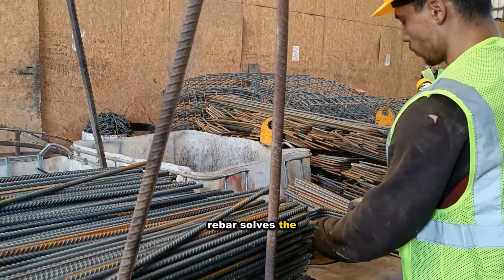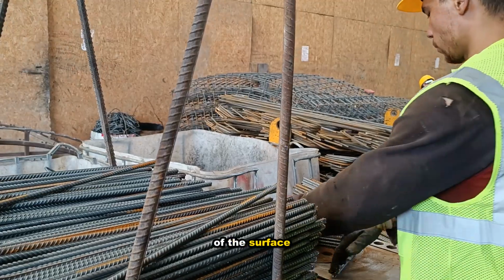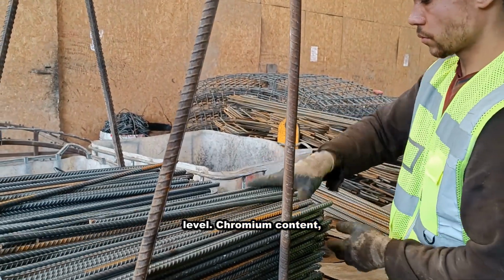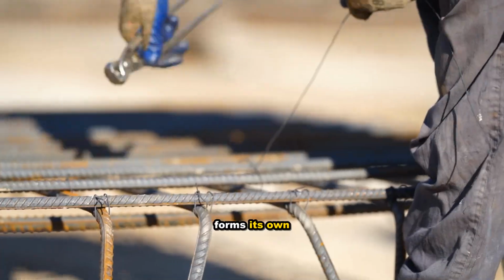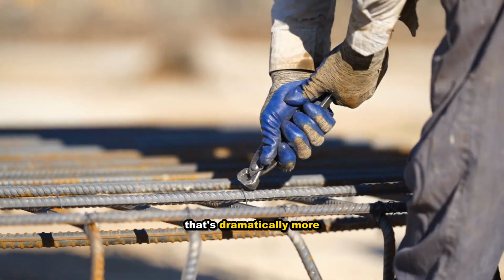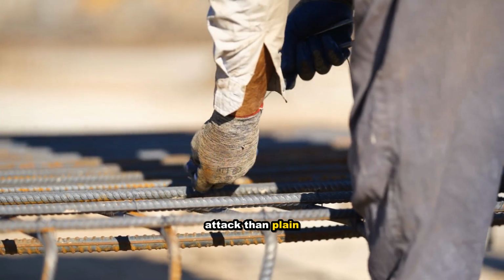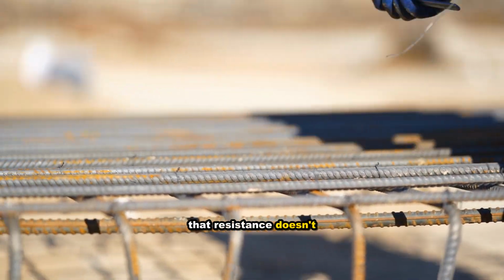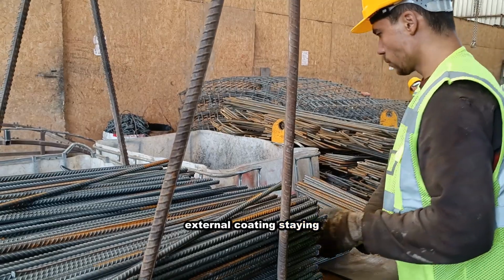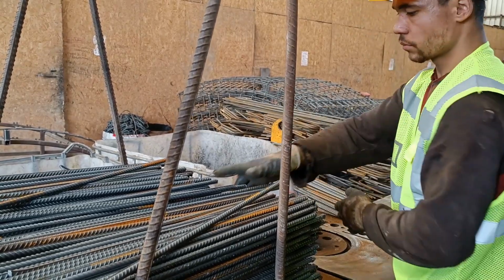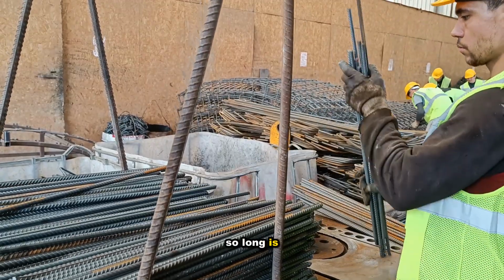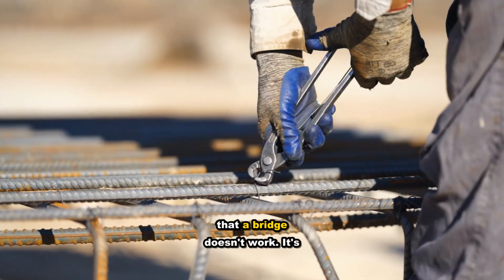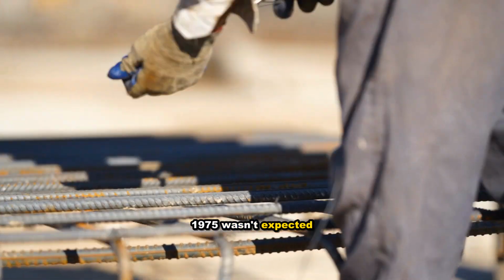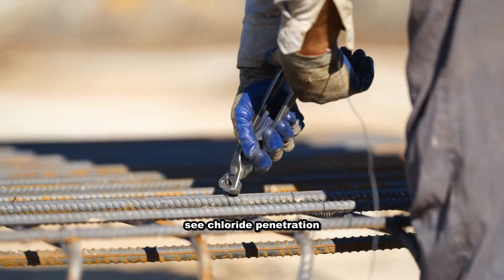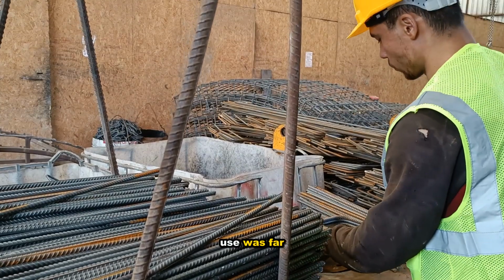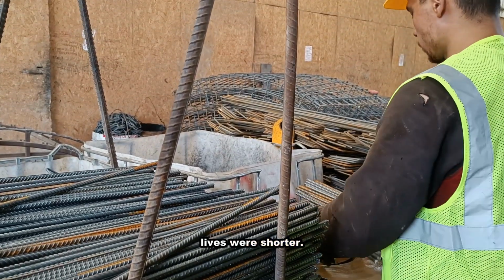Stainless steel rebar solves the problem at the material level instead of the surface level. Chromium content, typically above 10%, forms its own passive oxide layer that's dramatically more resistant to chloride attack than plain carbon steel. And that resistance doesn't depend on an external coating staying intact through construction. The reason agencies avoided it for so long is not that it doesn't work. It's that a bridge deck built in 1975 wasn't expected to survive to see chloride penetration at all, back when road salt use was far lower and design lives were shorter.